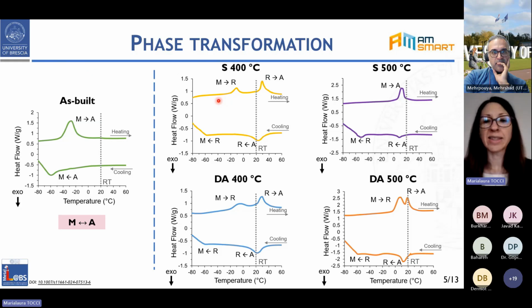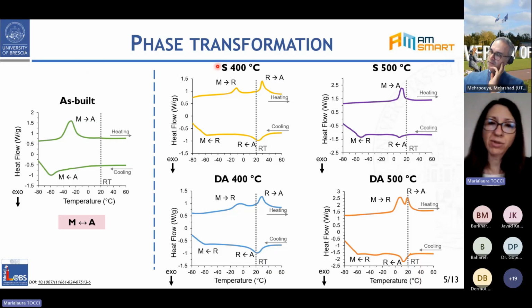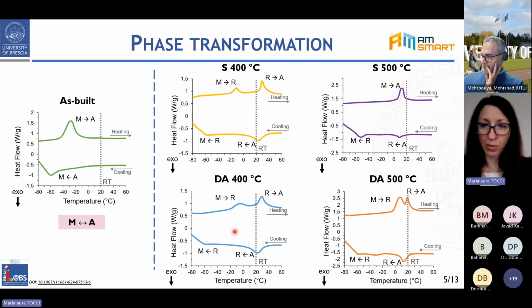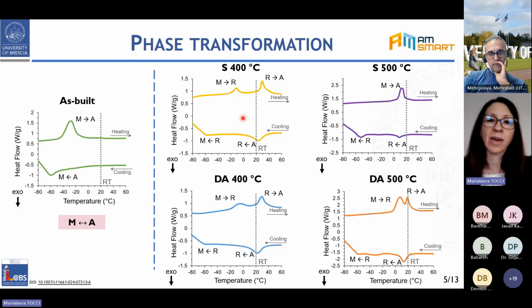So this is evident for all the heat treatments that we tested, and it is also evident, if we compare the heat treatment with and without the solution treatment but the same aging treatment, that the curves are very similar, if not superimposable. And this was a first hint that actually the solution treatment could be a step that could be avoided.